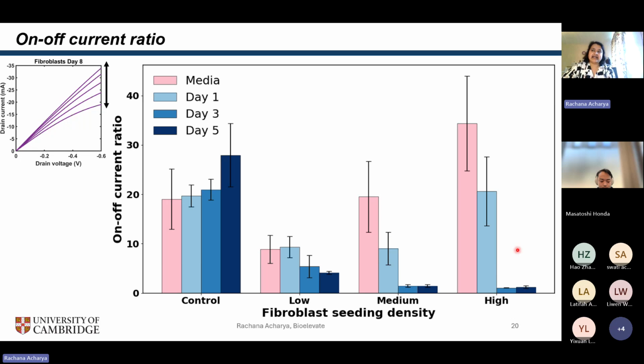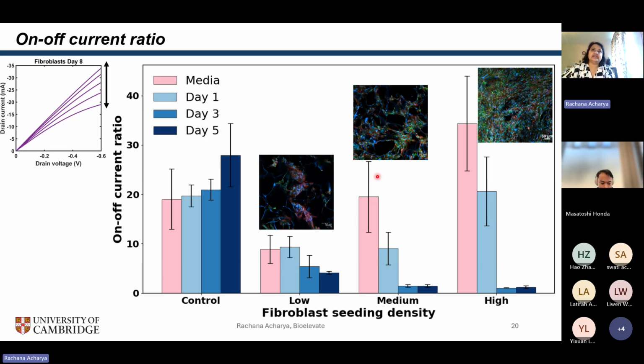But then in the medium and the high density samples where we had a large amount of cell growth, we can see that the on-off current ratio decreases quite rapidly compared to its media control. And if you notice for day 3 and day 5 for these samples, the magnitude of this ratio is almost 1, which means that the on current and the off current were almost the same. So it's completely blocking access of these cations into the polymer. And so again, here are zoomed in images of how these cells look on day 5 of their growth.